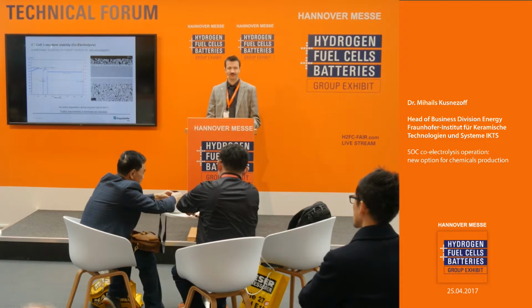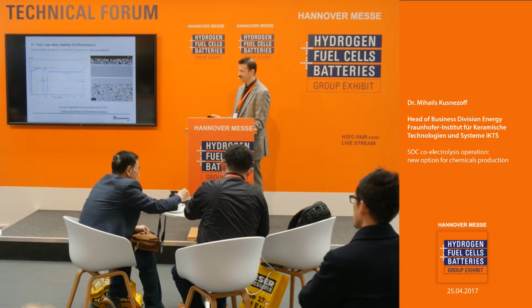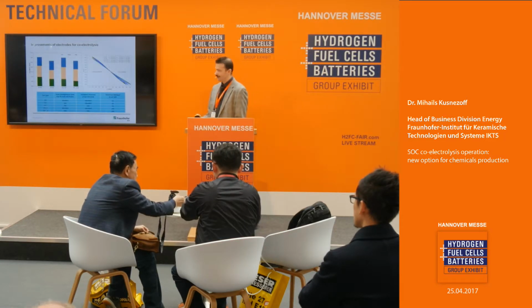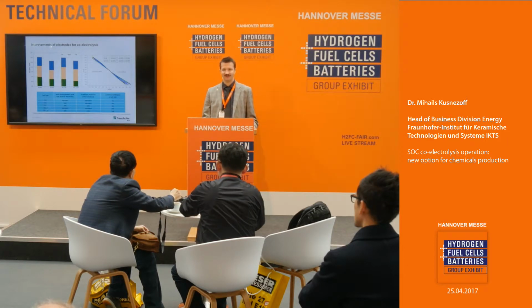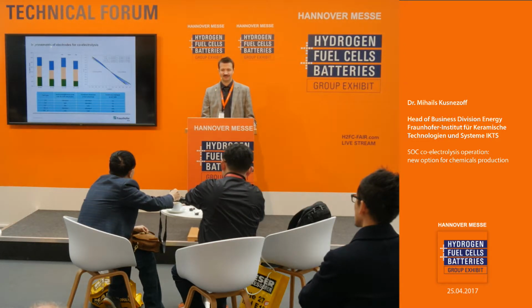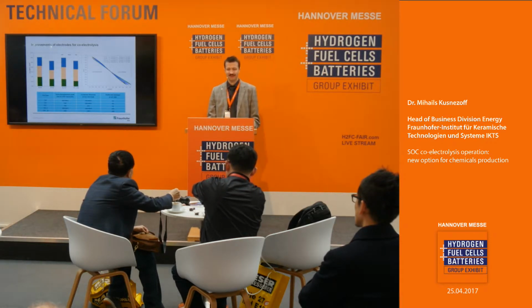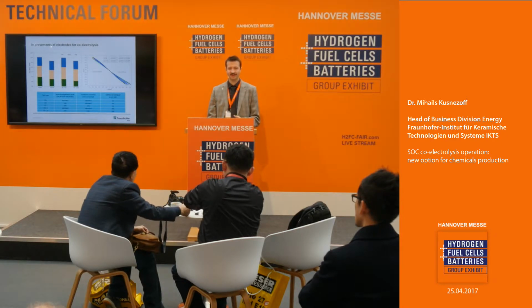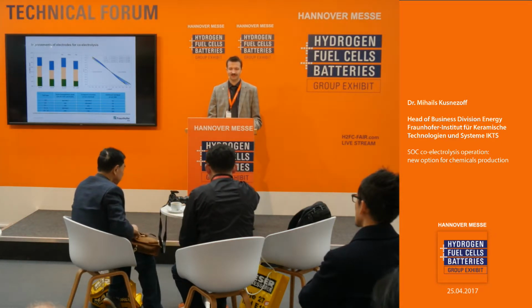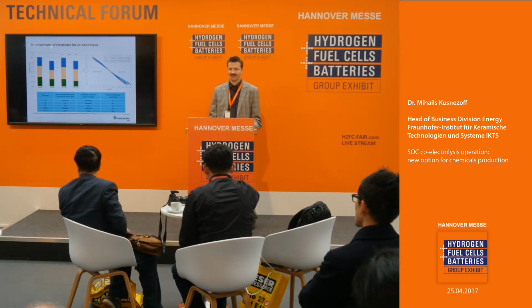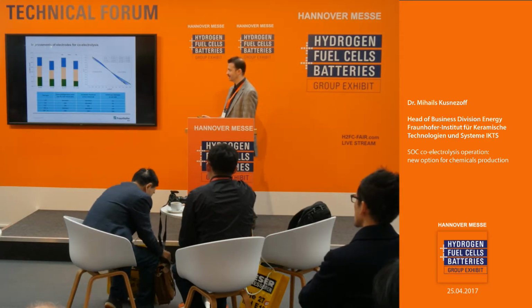These effects are also reversible, so if we put the cell in the fuel cell mode, then we don't observe it. So we wanted to investigate how we can diminish this effect and tried to change the porosity of the fuel electrode, and at the same time trying to improve adhesion of the air electrode, because it is known that in electrolysis operation, the air electrode can be delaminated from the electrolyte, especially at higher current densities.